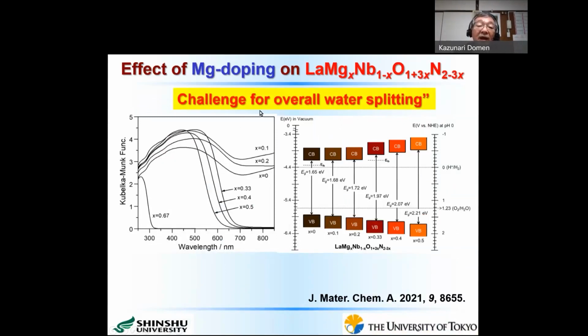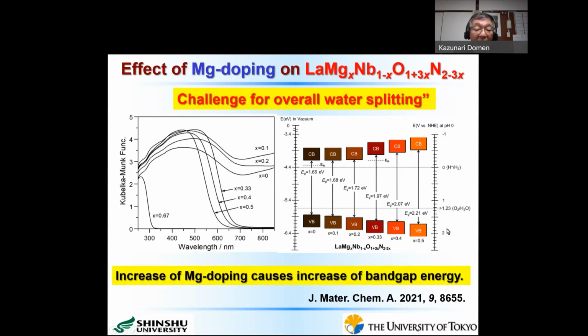In this case, we doped magnesium into lanthanum niobium oxide nitride. And as you see here, when we increase the magnesium content, this X value, from 0 to 0.1, 0.2, and then up to 0.33, the baseline becomes much lower, as shown here. And here I show the band gap energy measurement and also band gap positions for these materials. As you see, with the increase of magnesium doping from X equals 0 to X equals 0.5, the band gap energy is increased like this.